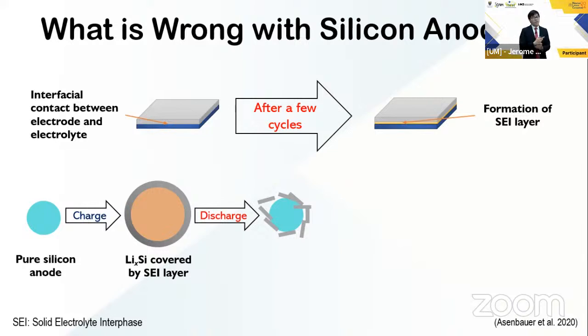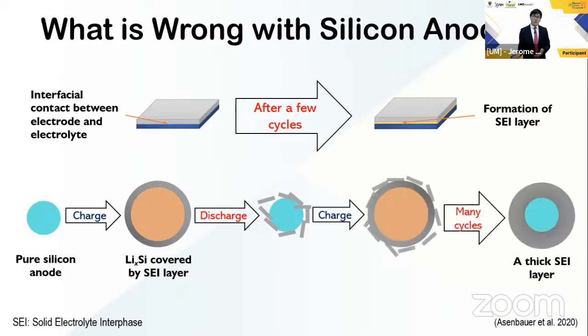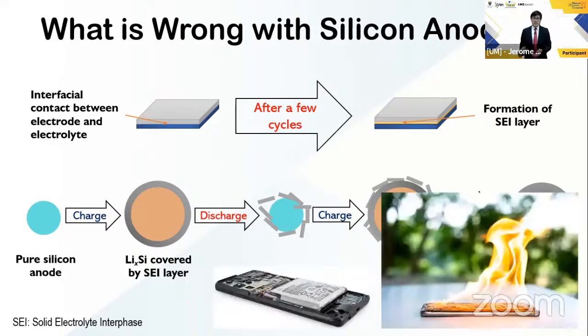So you're vulnerable to the formation of a new one, which is what happens when it expands again. When it is charged again, it forms a new SEI layer that is subsequently destroyed. And when you repeat this cycle many times, eventually you will get a thick and dysfunctional SEI layer that increases the internal resistance of the cell and causes great performance degradation. Now, what do these translate to in real life? It means a very swollen and a very hot battery.